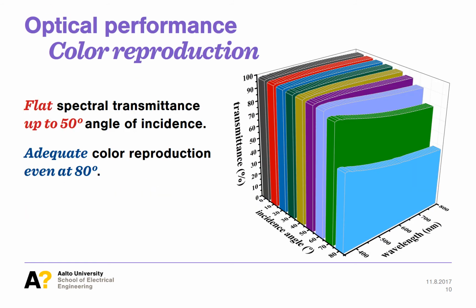The transmittance spectrum keeps a flat shape up to 50 degrees angle of incidence. The spectrum has almost negligible shape degradation at 60 degrees. And even at 80 degrees incidence, the color reproduction does not experience strong distortions. To our knowledge, grass-like alumina has the best omnidirectional transmittance within single-layer coatings.